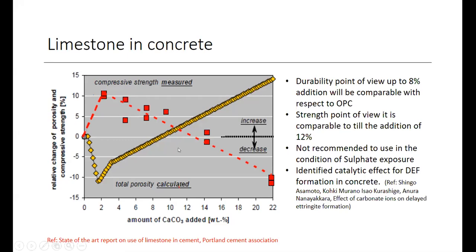But in terms of durability, when it comes to the level of 8% addition, afterward the porosity will increase. It means it reduces the durability. When it comes to strength, even up to the 12% level, it is comparable to the OPC. So in terms of durability, 8% addition will be comparable with OPC. In terms of strength, it's comparable at about 12%.